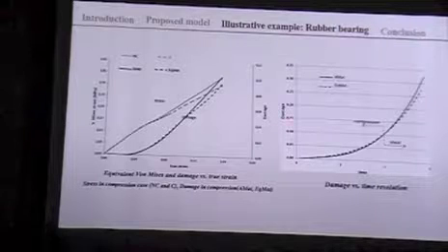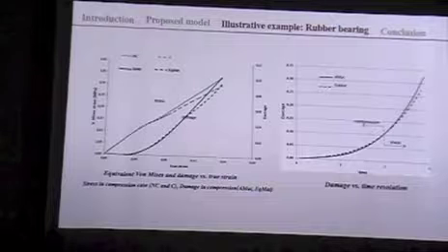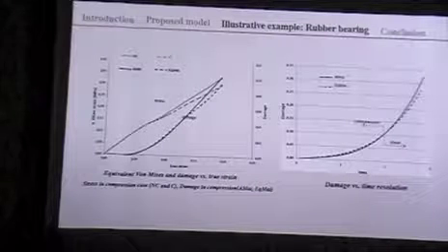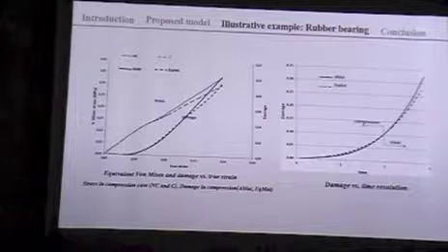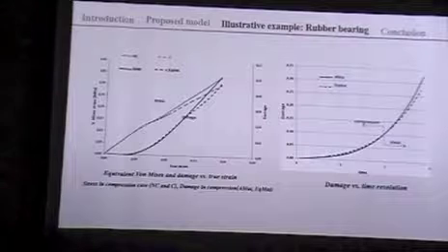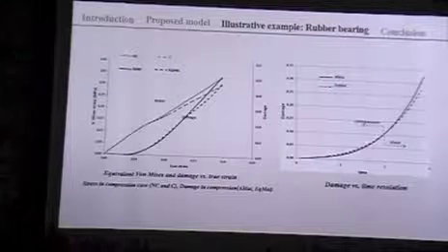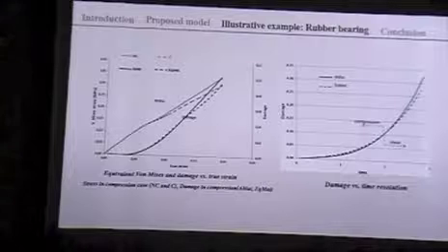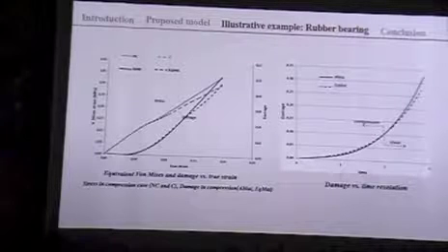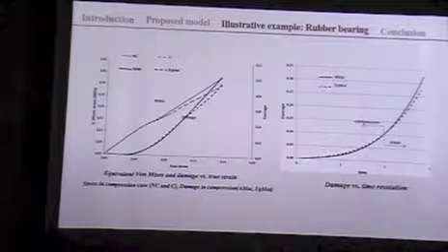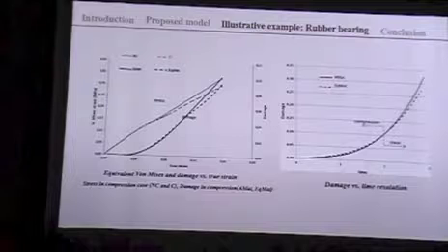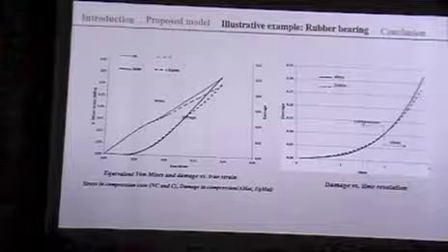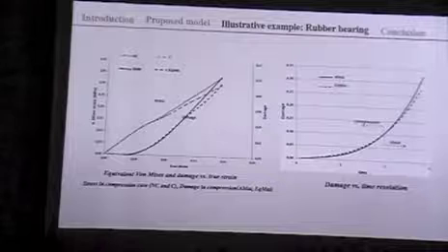Here we represent the damage evolution versus the time of resolution for the same integration point. We find that the damage changes position from compression to shear. This could be attributed to the slow drop of the overall stiffness, which is more sensitive in shear than in compression.